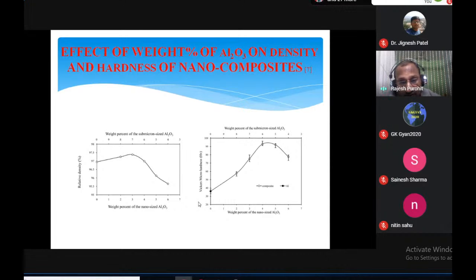Actually, most of the properties are very good at about 2.5 to 3.5 weight percent of alumina, and after that most of the properties go on decreasing. The reason is mainly that at higher weight percent, proper mixing does not take place. Also, if we fabricate by casting, then after 4 weight percent the melt generally rejects the particles. The volume of particles is too high, even at 4%, so they do not mix and either settle at the bottom or float on the surface. Segregation also takes place. Because of that, properties go on decreasing after 3 or 4 weight percent of the nanoparticles.